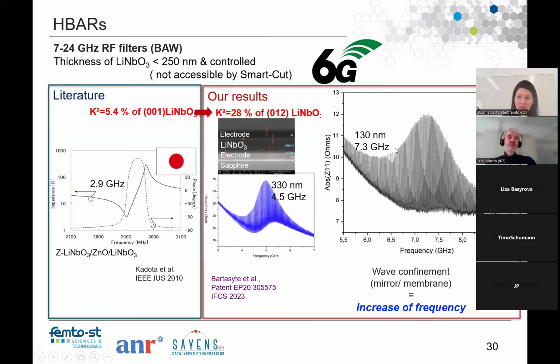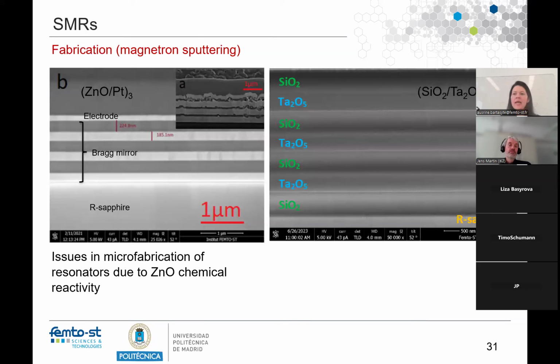If we go to 130 nanometer thick films, the size of the device is already 1000 microns, so impedance matching is very bad, and the signal, of course, is very bad because we are badly matched to our circuit. The film is very thin, but the frequency remains low, because it's an FBAR, so the structure is very heavy for a film to move, and the frequency is really damped. We also use platinum electrodes, which are very heavy, so we need to make a real TF-bar and so on to show the real performance of a film.